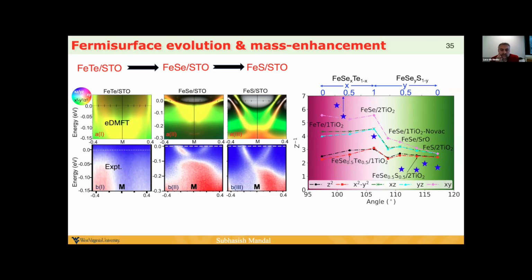Sure. Agree. Maybe if there's 2 more minutes, I would like to ask what kind of functional the DFT part of the calculation uses. GGA, LDA? We use LDA for the DFT part using wien2k. Okay, because I think there is evidence that in all these iron-based superconductors, which are some sort of semi-metals, the overlap between the electron and hole bands is slightly overestimated by these methods.